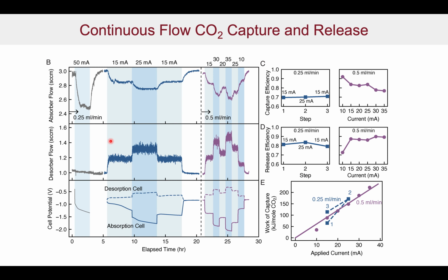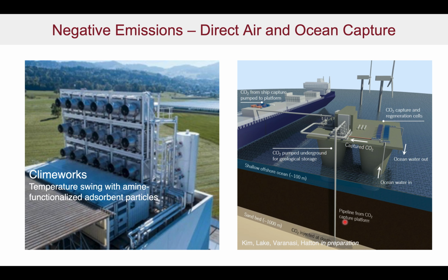And we've shown that this works. There's still some work to be done to optimize it, in particular this desorber flow, how much CO2 we are releasing. We can show this as a function of current in that desorption unit. As we increase the current, going from 0 current here to 15 milliamps, 25 milliamps, and back to 15 milliamps, we can see we can regulate rather well the actual rate of release of the CO2 in the system. The energetics aren't as favorable at this particular point. We're still pretty high, about 100 to 150 kilojoules per mole, much higher than we'd like, but it's something we can work towards. Now that's all just showing the overall concept.